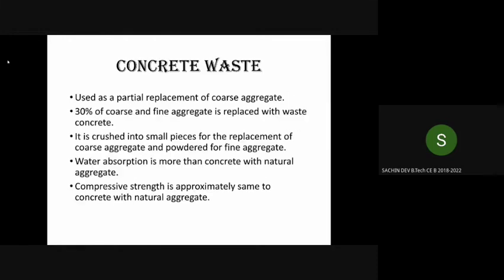And the coconut shell provides a compressive strength of 24.2 MPa. And the next one is concrete waste. We use concrete waste as a partial replacement of coarse aggregate and fine aggregate. About 30% of the coarse aggregate and fine aggregate is replaced by concrete waste. The crushed concrete waste is used as coarse aggregate, and the powdered form is used for fine aggregate. The water absorption of concrete waste is more, but the specific gravity is low. The compressive strength is approximately the same as that of the concrete produced with normal aggregates.